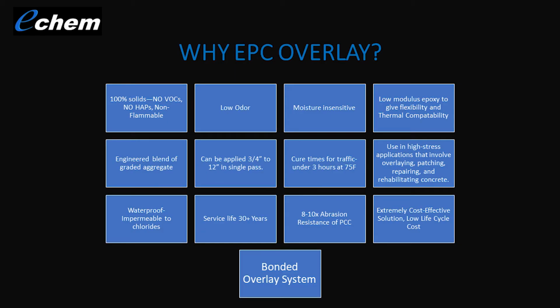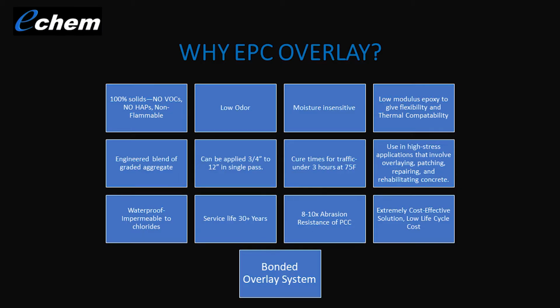So why EPC overlay? We developed EPC with a very specific target. We wanted to make sure it's going to meet future environmental concerns. We have zero VOCs, no HAPs, very low odor, rapid curing, and we're moisture insensitive. It's a rapid return to traffic. In 3 hours at 73 degrees, we're traffic ready. So if there are time constraints and concerns for short traffic closures, this is a very well-suited product.